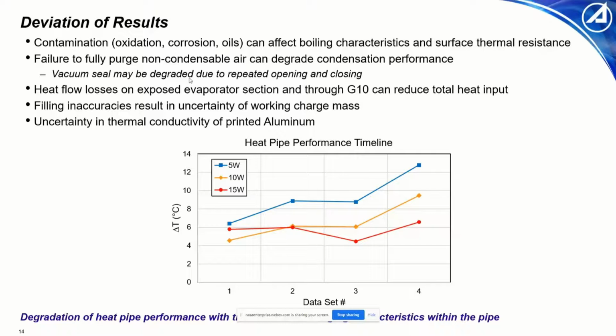It's important to note this was with very similar charges, and charge sensitivity analysis was performed, so deviation in charge mass was not the source of this. It truly was performance degradation.